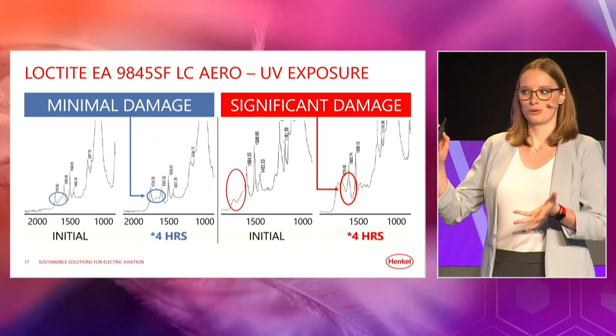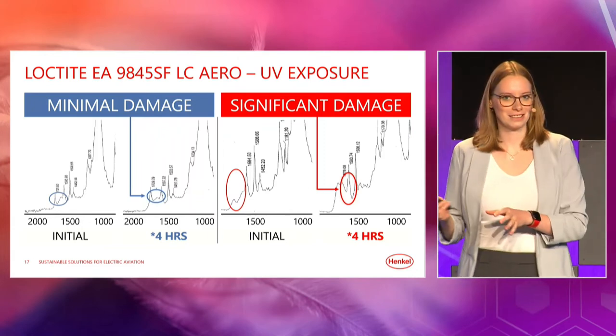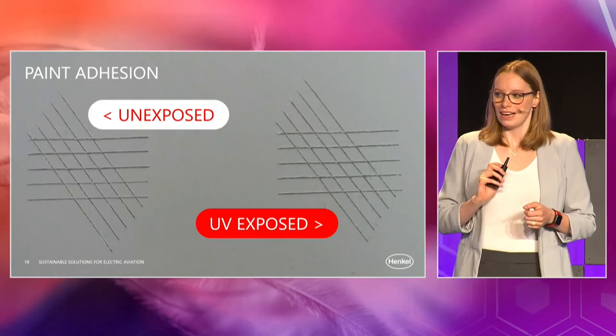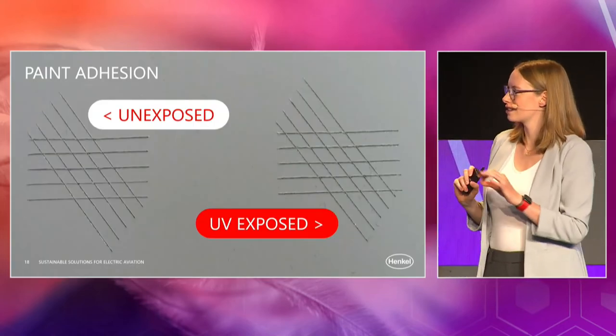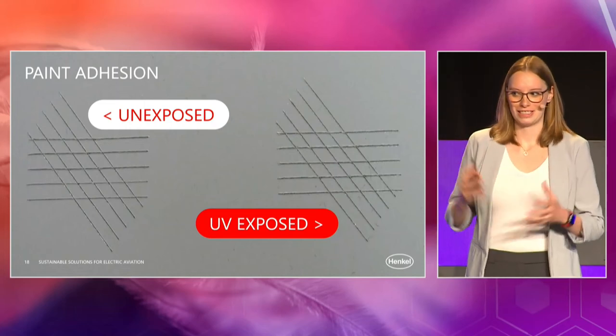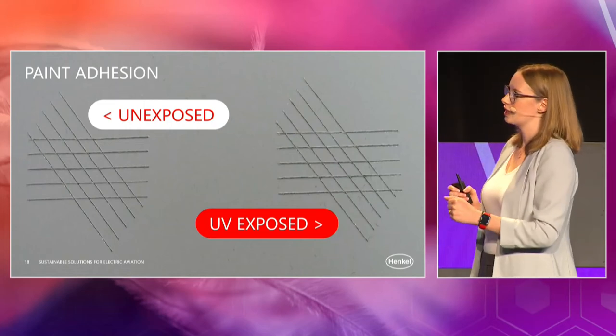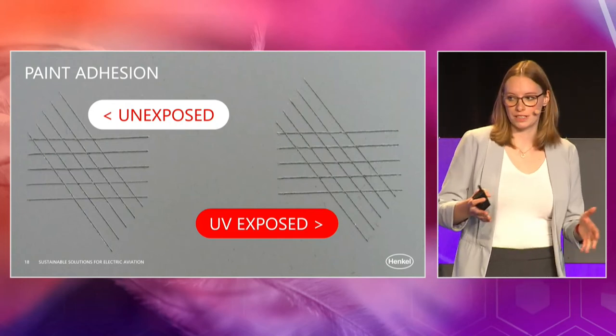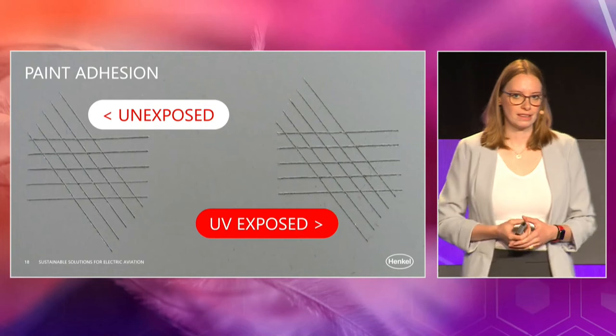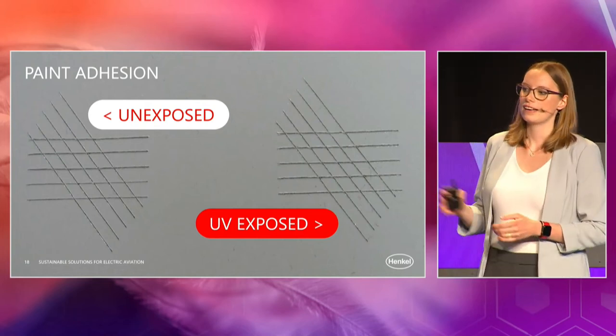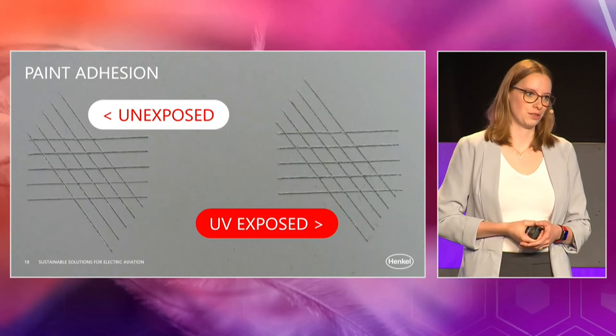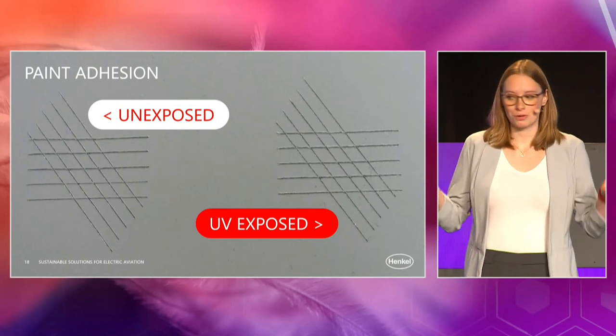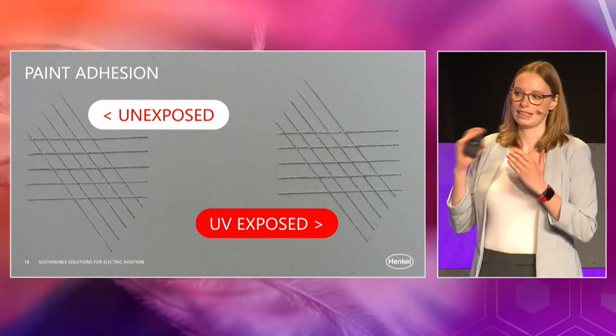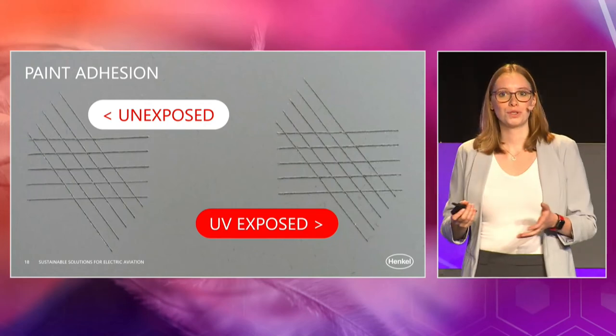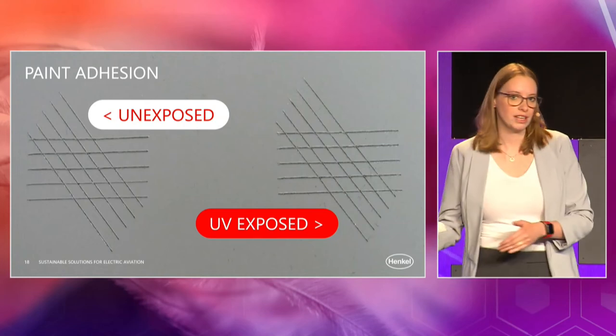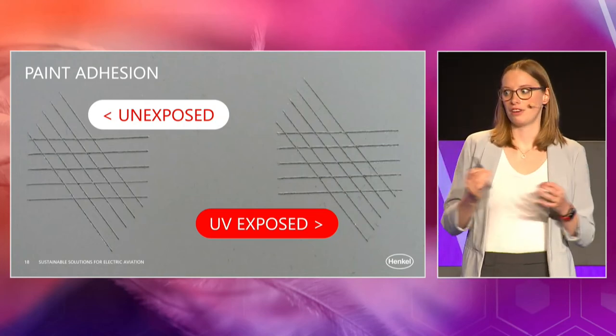And to translate these very technical graphs into real-life pictures, I have here this paint adhesion grid test method. And on the left side, you see the unexposed surfacing film, and on the right side, same method, 4 hours of UV exposure, and afterwards, this grid was carved into the film adhesive. And as you can see, no visible damage. So it looks actually the same. So we can be sure that the properties after UV exposure and before are very, very much the same.